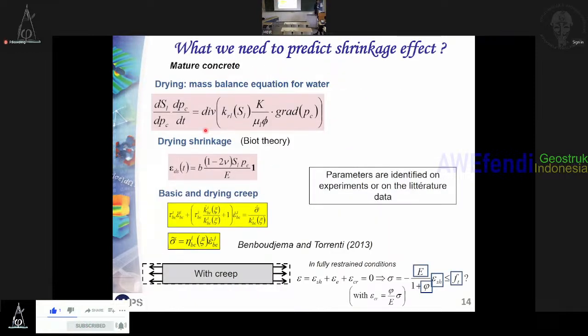Yes, I completely agree with you. It would have been better to end the drying phase in order to perform the test without gradient, in a perfect world. For 10 centimeters, it's between 6 months and 1 year to reach the equilibrium. Yes, my experience as well. So it's not only numerical simulations, but we have also done some experiments.